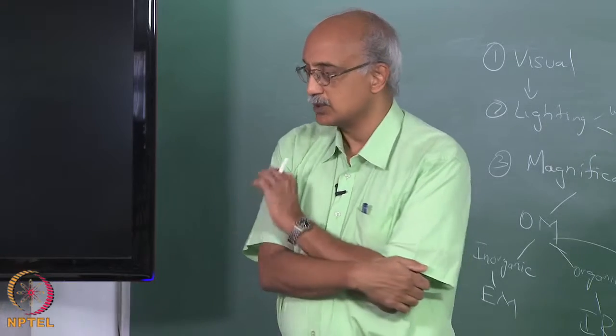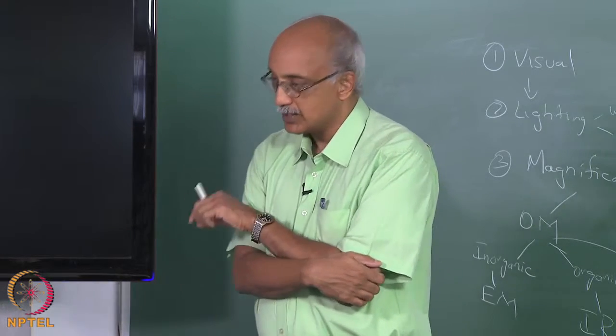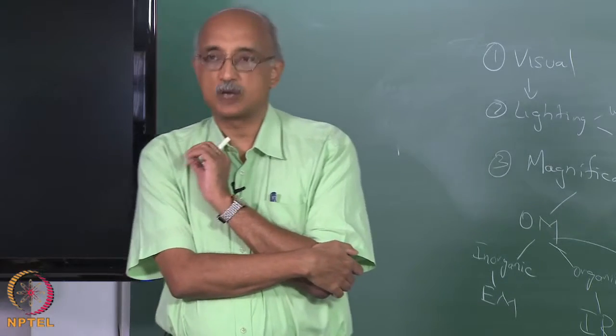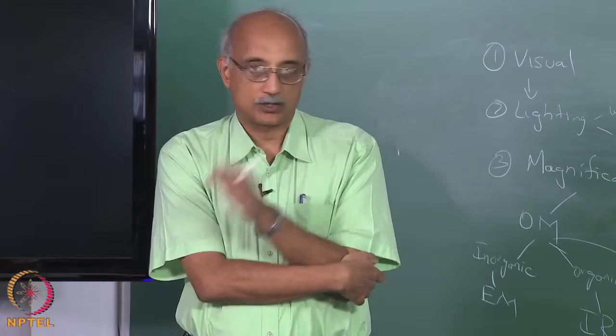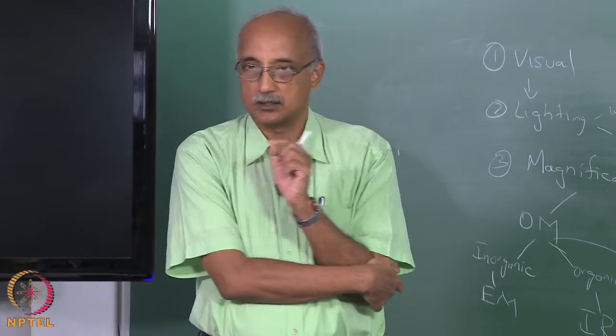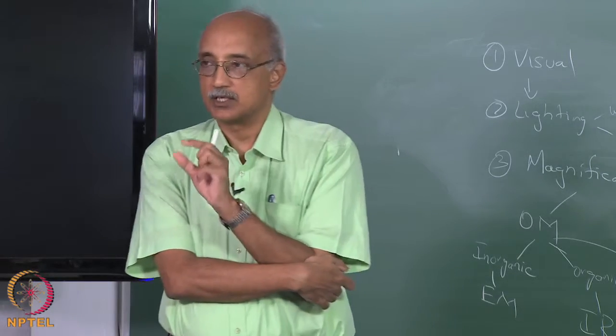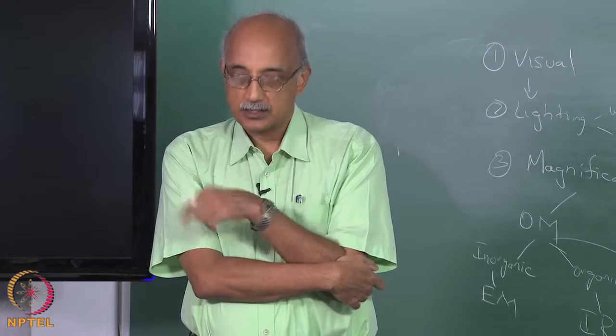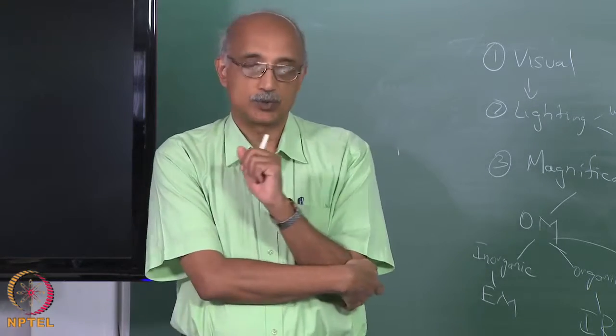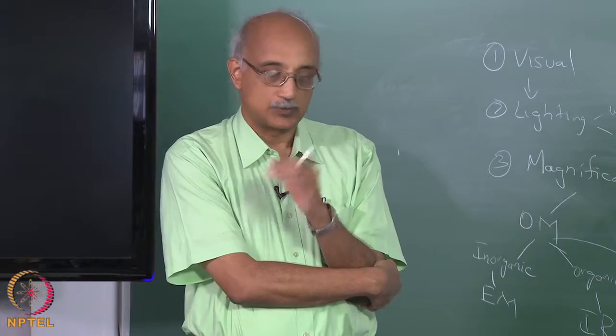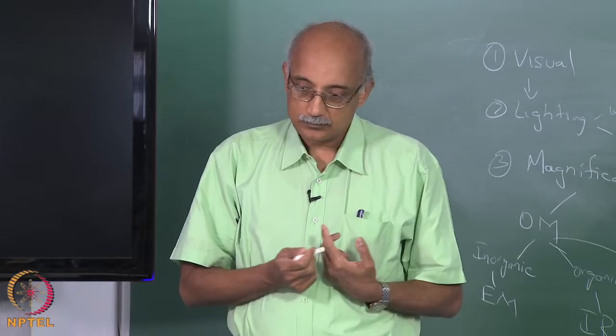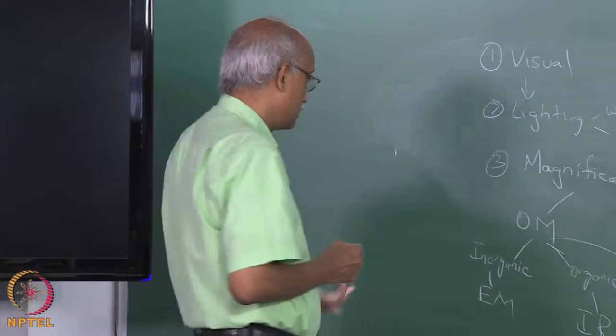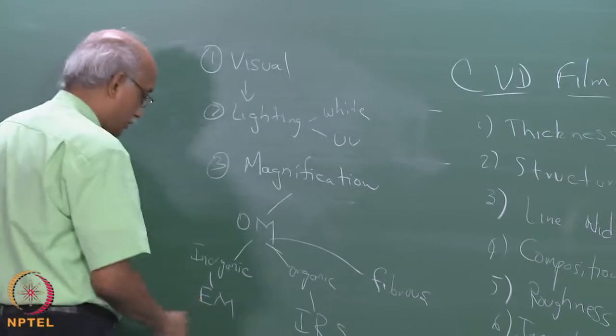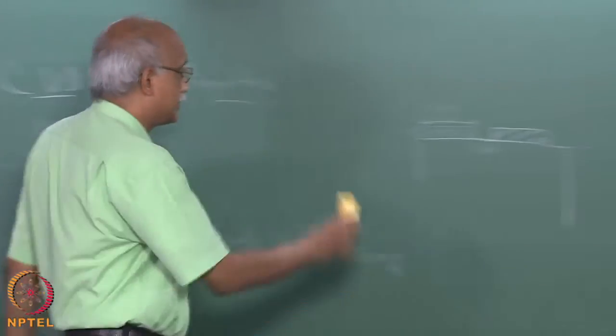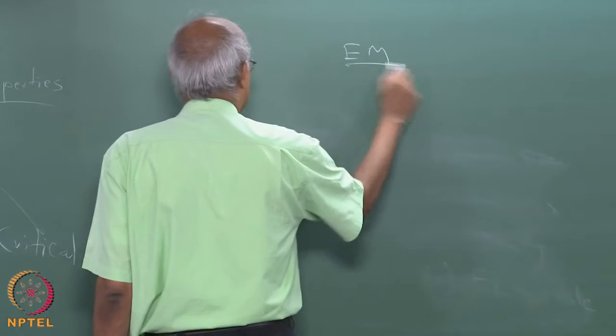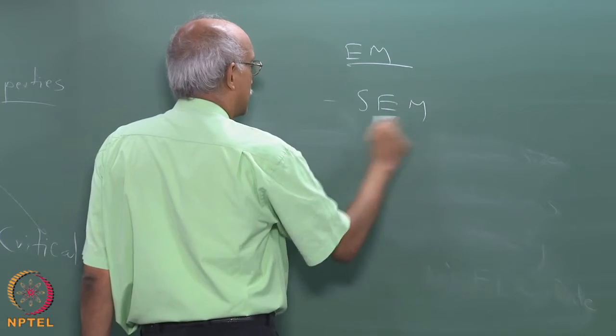Of course, nowadays both EDS as well as WDS apparatus are coming with what they call a carbon window, which enables it to detect all the way down to carbon. So, the range of atomic numbers that we can detect using SEM and EDS/WDS is constantly being improved, and up to carbon is now detectable. So SEM, TEM are certainly possibilities for analyzing samples. So under electron microscopy, SEM and TEM are the most widely used.